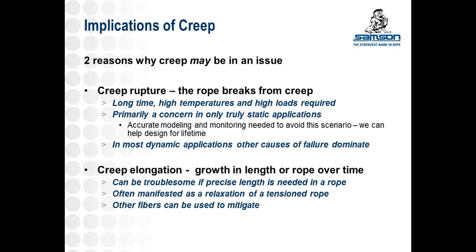There's really two reasons why creep may be an issue to a user. The first thing that comes to mind for most people is, is it going to rupture? Is my rope going to break due to the creep phenomena taking place in my fiber? And the truth is that really, for most cases that we see users using our rope, that's not going to happen. It requires long times, high temperatures, or high loads.